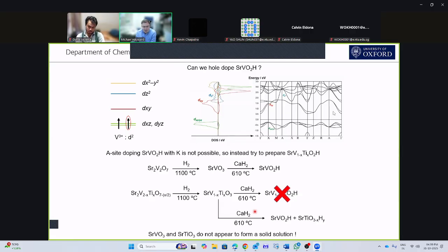What we find in this final reduction step is that we don't get the mixed titanium vanadium oxyhydride. What I get is a vanadium oxyhydride and a titanium oxyhydride. What that shows us is these two perovskites don't actually mix, which is a surprise because the literature reports say that they do. But let's see what's going on a bit more closely.